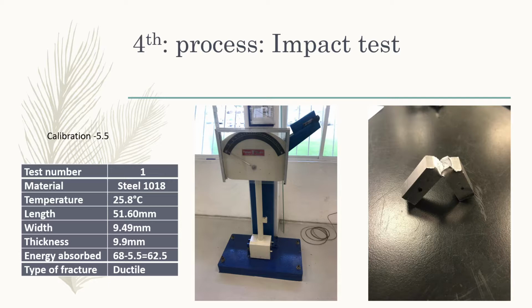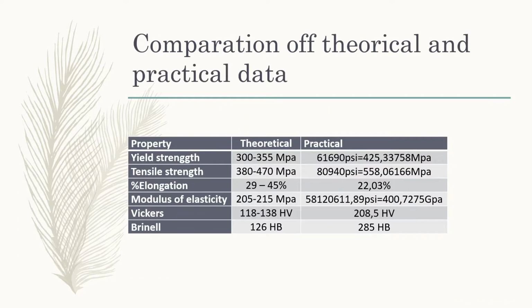For the impact test, we do it at room temperature, which was 25.8 Celsius. And the energy absorbed by the piece was 68, but we had to subtract the calibration, which was 5.5, and the result was 62.5. So the type of the fracture was ductile.